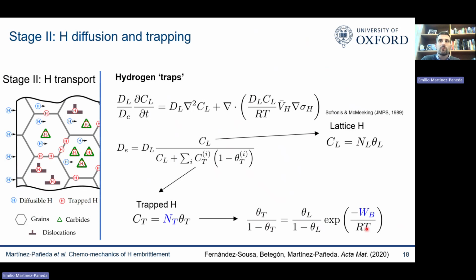And the trap binding energy. This tells you how energetically favorable it is for a hydrogen atom to go to a grain boundary or a dislocation or a carbide. And this is something that we can measure using TDS, thermal desorption spectroscopy. And we have developed something that we have in our lab.